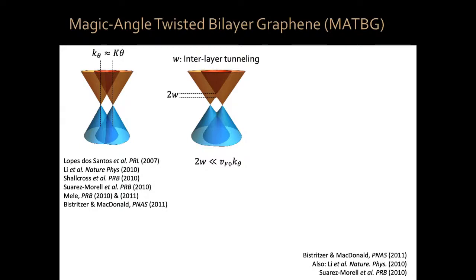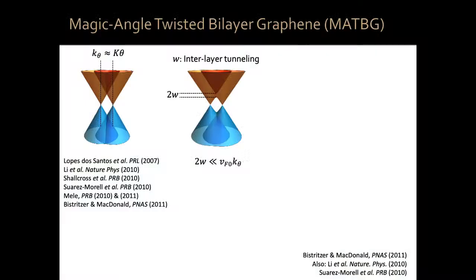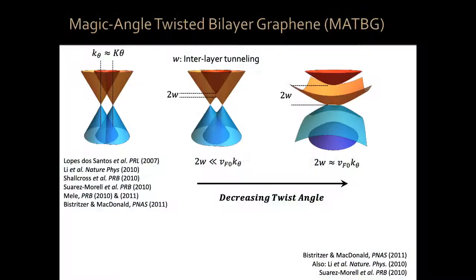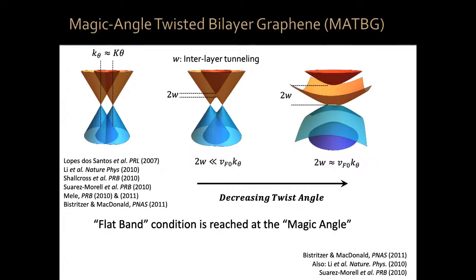This is the same thing as bonding antibonding states in a hydrogen molecule, except that these are bonding antibonding states in a giant graphene molecule. Now, the situation depicted here is for when this interlayer tunneling is small compared to the energy of that crossing point. But as you decrease the twist angle, these two points get closer and closer, and that lower band gets pushed down to lower and lower energy until you reach a value for which the interlayer tunneling is of the same order as that energy point there. Then we say that a flat band condition has been realized, and the angle for which that occurs is known as the magic angle, which happens to be 1.1 degrees for graphene on top of graphene.